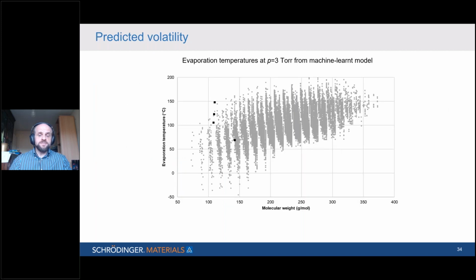And this is the data now. Obviously, it's hard to show 50,000 data points on one graph, so please excuse the lack of resolution. But again, I'm showing the predicted temperature against the molecular weight. And the black dots are the existing precursors that are often used in MLD. The first thing we see, of course, is that most of these data lie somewhere between 50 and 150 degrees C, regardless of molecular weight, really. So there's a weak dependence. The very most volatile ones are light and the least volatile ones are heavy. But in between, there's a huge range of molecules that have all manner of different R groups and different masses. And so this isn't really the most important factor, I would say, in deciding whether a molecule is volatile or not. So some of these results might make us rethink how we understand volatility.